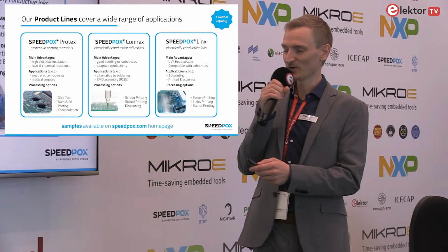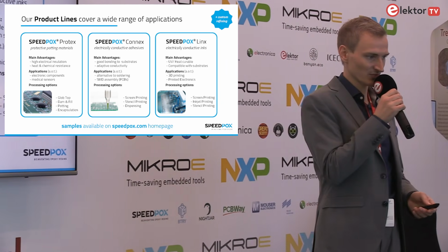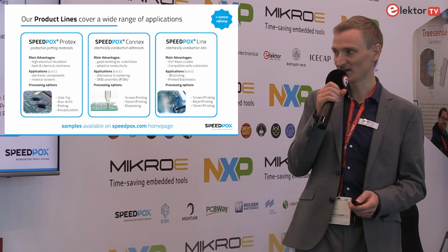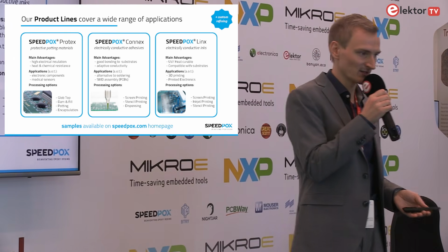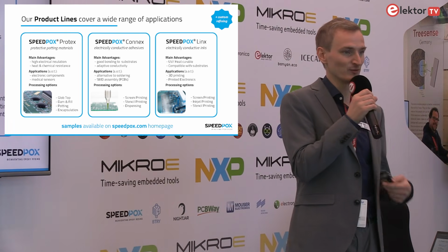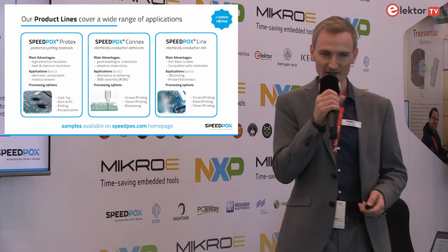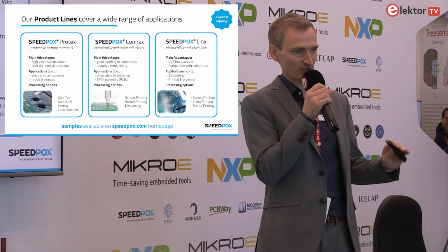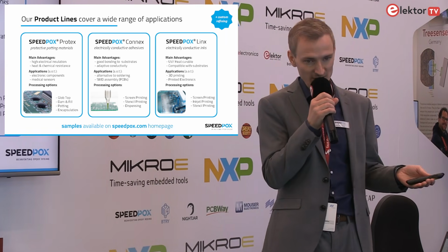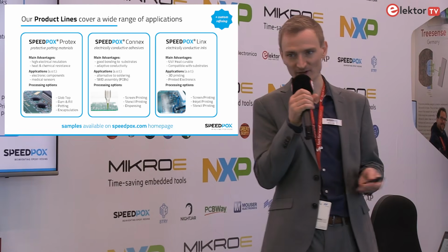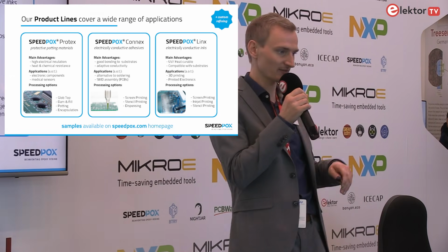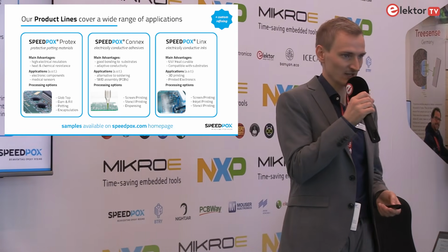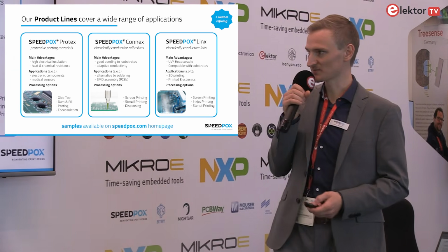And here, what really sets us apart from the traditional epoxies is that we can cure even highly filled systems with our UV stimulus. And we can make this UV curing wave go through shadowed areas, which is filled with flame retardant or heat conductive materials. So we can use highly filled systems as well.